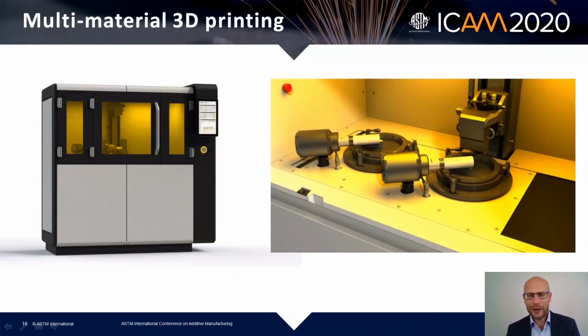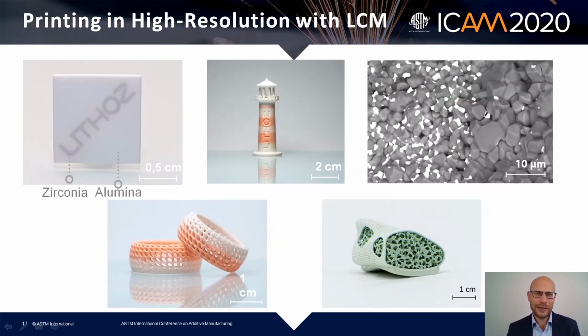Something we have lately been working on is also very interesting: multi-material 3D printing. Here you see our CeraFab Multi 2M30, where you have two beds with a cleaning station in between, where you can really print two materials in different layers or even in the same layer, as you can see here. For example, on the left hand side you see zirconia and alumina combined. So the Lithoz is here written in zirconia in the same layers as in alumina.